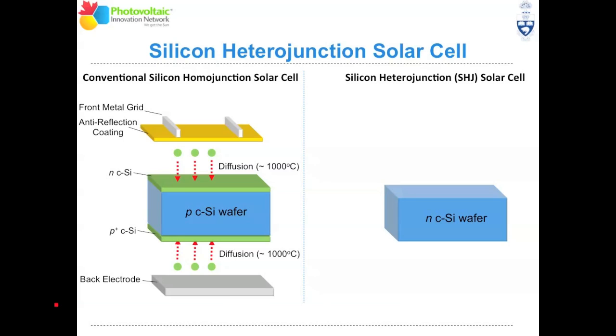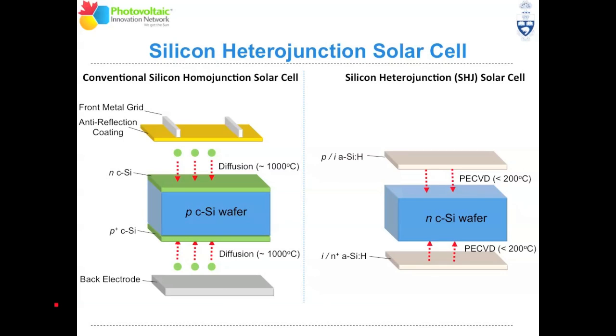Now, the silicon heterojunction solar cell, you start off very much in the same way. You can use a P-type or an N-type wafer. N-type tends to be a little bit more commonly used, but either would work. But this is the main difference. Instead of using the high temperature thermal diffusion process to form the necessary rectifying and back surface field junctions, you use a very low temperature process.